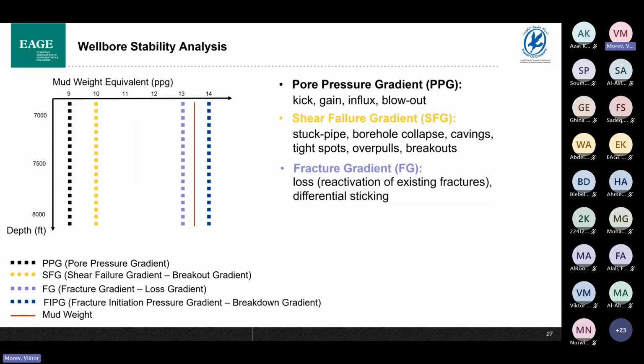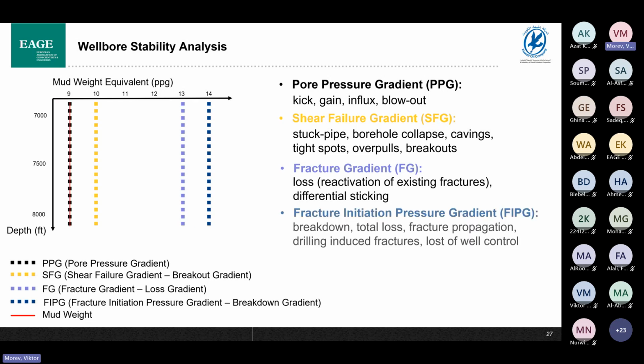Another scenario: when I increase the mud weight higher than the fracture gradient, higher than the loss gradient, I start to reactivate existing fractures and may start to get losses, or if the formation is depleted and permeable, I can start getting differential sticking. And in the extreme case, when my mud weight is so high that it's higher than the fracture initiation pressure gradient, at this point breakdown is happening.